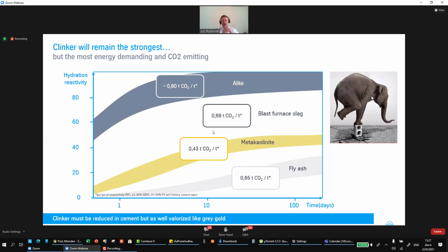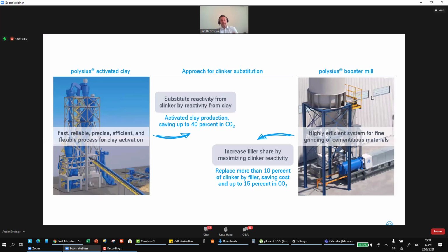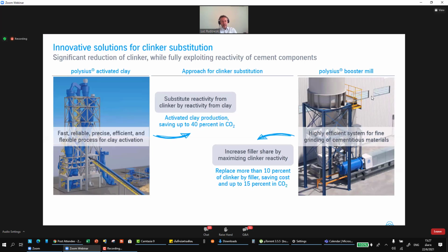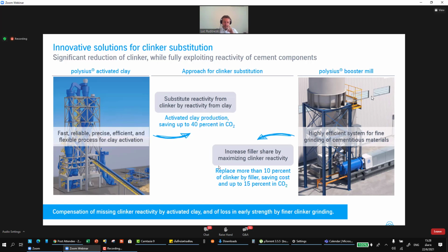So our proposal, in fact, is to combine both technologies here. First of all, what we call the Polysius activated clay, which is a flash calciner producing activated clay as a substitute for reactivity from the clinker. And on the other side, to optimize the reactivity of the remaining part of the clinker, which can be used either to push further the clinker reduction factor when using activated clay, or adding more filler if we are talking about a limestone additive.